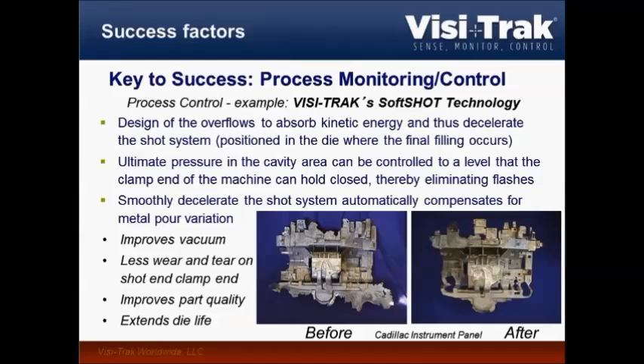As I mentioned before, at the end of the fast shot, it's very important that we don't get a whole lot of flashes, because the flashes will ruin our die, and especially they will ruin the vacuum. So Visi-Trak offers the so-called soft shot technology that helps decelerate in the end, and hence improve the vacuum and generate less wear and tear on the shot and the clamp and the dies.